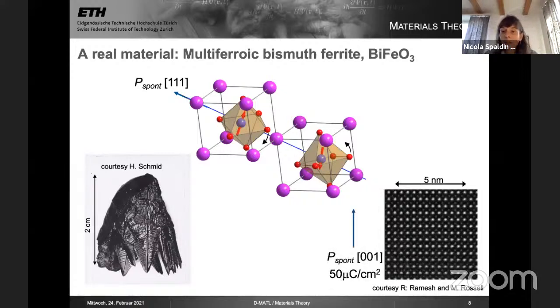And so it was measured that there is indeed a very large spontaneous ferroelectric polarization associated with these bismuth ferrite thin films. It's 90 microcoulombs per square centimeter along the 1-1-1 direction, or perpendicular to the film direction along the 0-0-1 direction, perpendicular to the film, it's around 50 microcoulombs per square centimeter. Okay, so now with the thin films, one can really do science and engineering with the bismuth ferrite.